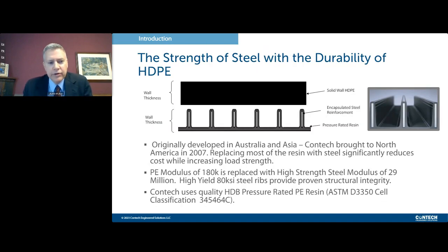And this technology was originally developed in Australia and Asia, and Contech brought it to North America in 2007. And the idea is to replace most of the resin in the pipe wall with steel, and this significantly reduces the cost while at the same time increasing the strength. And we recognize that high-density polyethylene is very corrosion resistant. It's very abrasion resistant. In fact, it is the most versatile and widely used piping material in the world today. However, where it struggles is in structural integrity in larger diameters. The pipe wall has to be very thick.